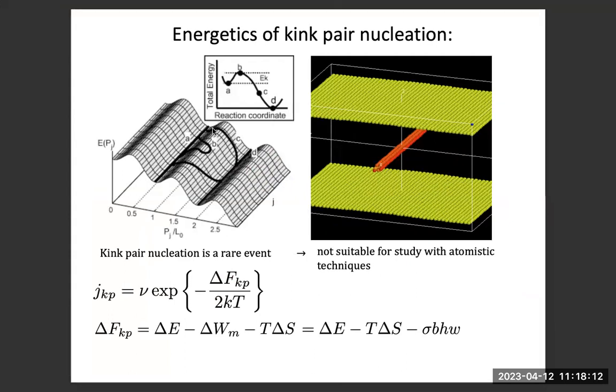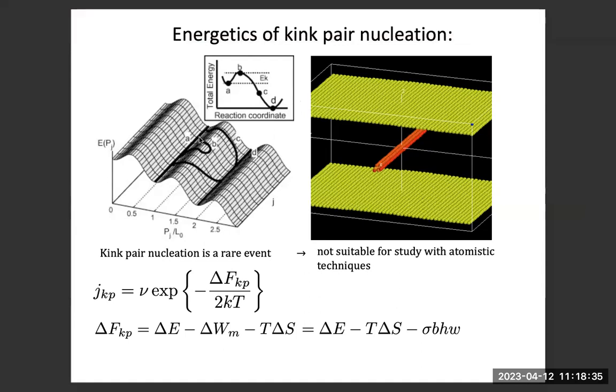So here you can see a better representation of kink. Our initial dislocation is at A, and the dislocation wants to go to lower energy states. Firstly, it creates the edge parts, which are, let me try to annotate, these are the edge components. Then we have kink formation here.